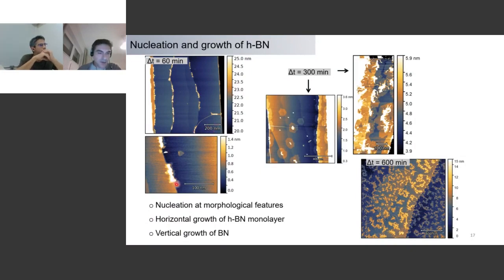If you have a look here in this AFM image, you also see very tiny islands forming where the height of these islands would correspond to a monolayer, an atomic layer of hexagonal boron nitride, about 0.35 nanometers. And only when we grow for a much longer time, which is pretty long here, and this is because we use a very low boron flux and nitrogen flux in this case. So it's expected you get this very low growth.